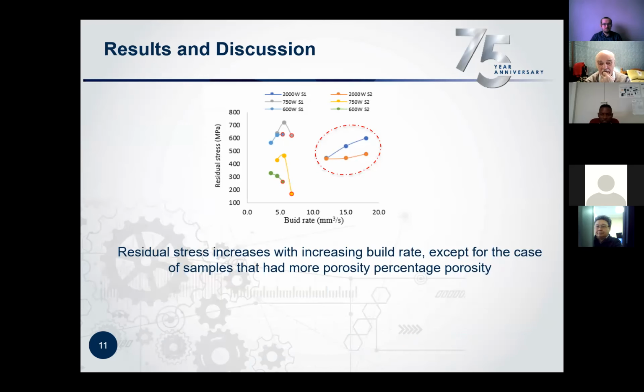And then here we try to see if we can see any trend when we look at the residual stresses as a function of the build rate. Not so obvious relationship because of the existence of porosity in our samples. We know if you have high porosity in your samples, it's going to relax the stresses in your part, and then this is going to influence your measurement results.